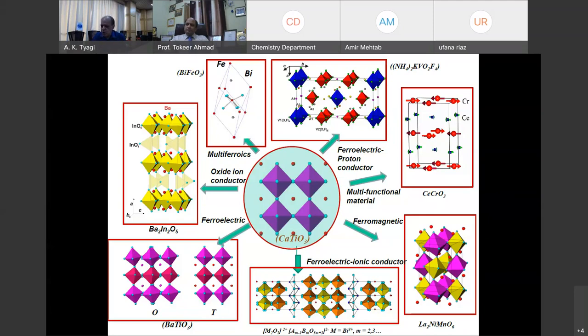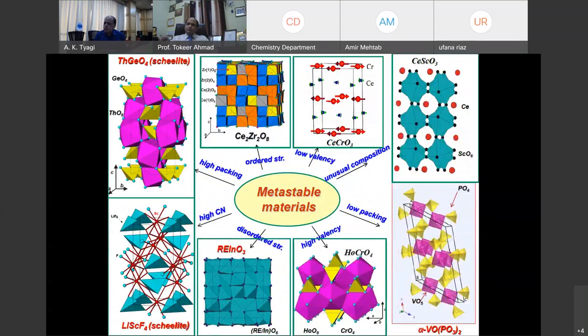Now I move to approach number two, metastable approach. Just to share with students, please don't get confused. Metastable materials are not unstable. They can be extremely stable as far as kinetics is concerned. Classic example is diamond and graphite. When I give a talk in person, I ask students which is more stable, diamond or graphite. People say diamond, which is not correct. Thermodynamically speaking, graphite is more stable than diamond. But diamond is diamond. Diamond does not become graphite because diamond and graphite have a very high activation energy barrier.